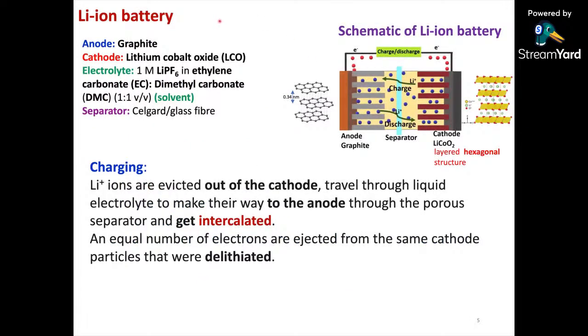Okay, all of us know the lithium-ion battery, with reference to the commercial one. We have the anode and cathode, where I will take LCO as the cathode and graphite as the anode. During charging, the lithium ions move away from the cathode, pass through the electrolyte, and get intercalated in the graphite, between the graphene layers whose separation is 0.34 nanometer. This is an intercalation process, and an equal number of electrons are ejected from the same cathode particles that were delithiated. This is the anode, cathode, and the electrolyte that people normally use, including the separator.